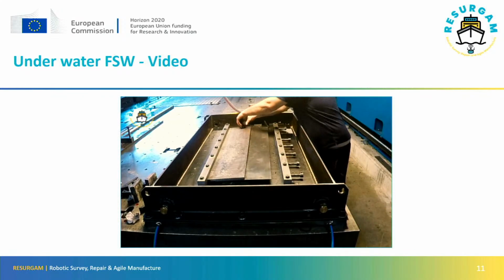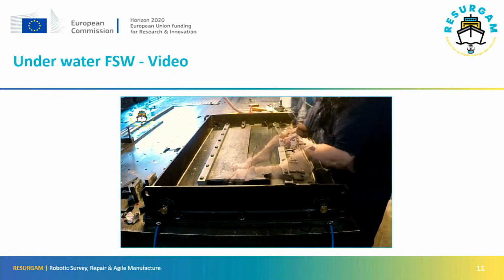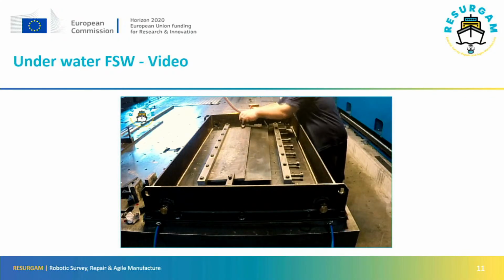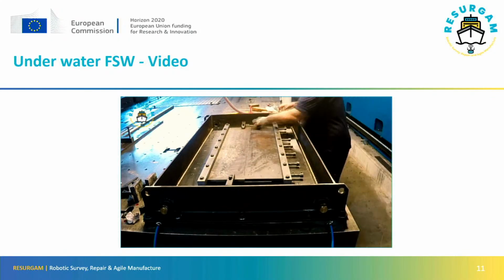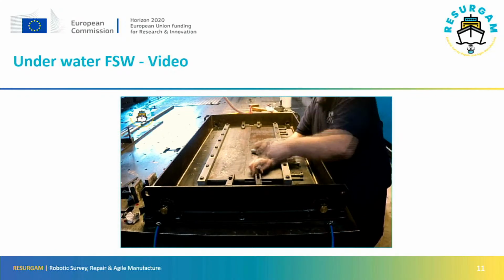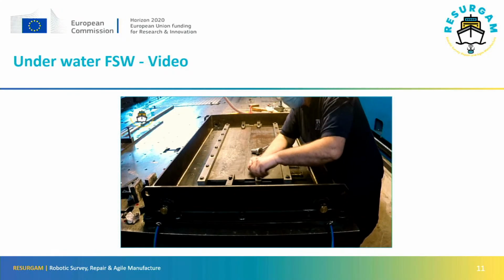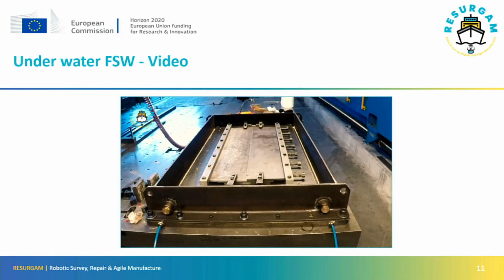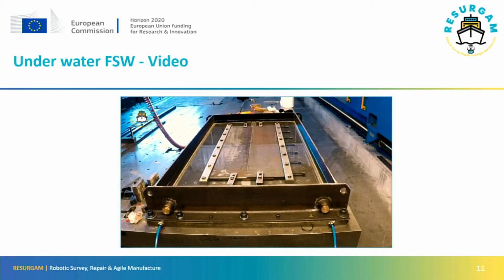In the short video running now, we see a test coupon of 12mm thick carbon steel being butt welded from two separate plates in TWI's laboratory. The steel plates are first secured side by side in the welding jig. The plates have simple square butting edges. There's no need to undertake a V-groove preparation for friction stir welding.